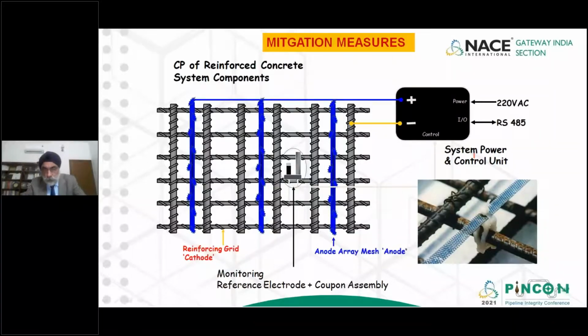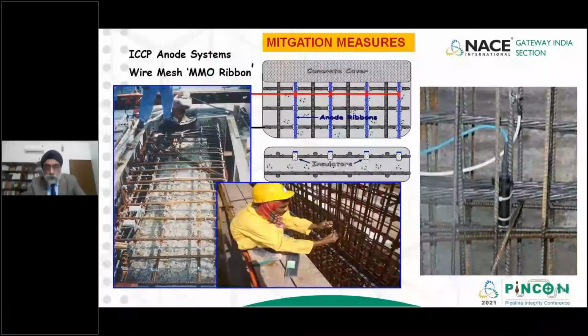Using ICCP for CP of reinforced concrete structures is a very sophisticated technology. There are NACE standards written around it. There are ISO standards written around it. So in case any asset owner wants to use this technology, proper designs are required, and it's a mature technology to protect rebars. Again, some photographs are being shown, where the mesh anodes have been kept on the rebars. On the right-hand side, you can see a silver chloride reference electrode embedded in concrete.